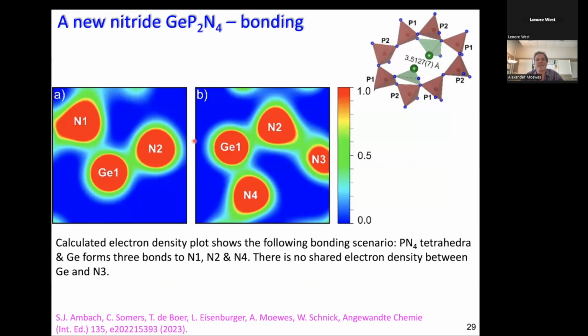M stands now for any kind of material. Calcium, strontium, barium, these materials have been realized in this class of MP2N4, phosphonitrido or nitridophosphates, they are called. And so this was the first time that this was realized with germanium. Again, what is typical in these structures is that you have these tetrahedral corner-sharing nitrogen sitting on the corners. And then in this case, there is always one element inside here, the phosphorus.